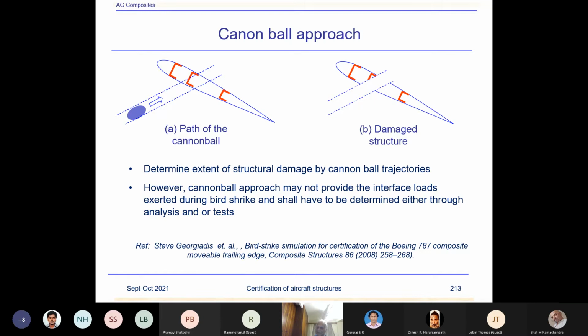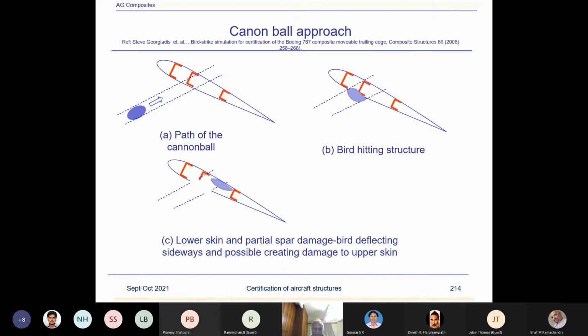And then you determine the residual strength to satisfy the damage tolerance requirement, which requires 70% of the limit load plus 40% of the gust, all those criteria, 25.571E, which I have presented in my previous slides in these notes. Another part of the cannonball, various damages, basically, when the bird just goes away and slips, creates damage at other places. All these scenarios are investigated and analyzed in order to show the compliance for bird strike damage to the structure.